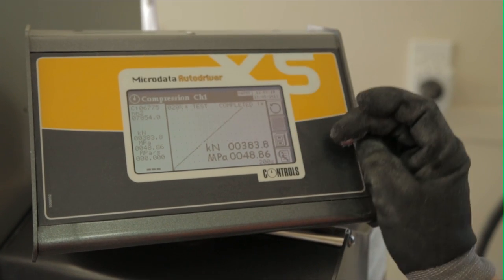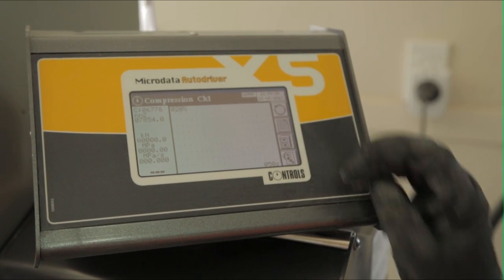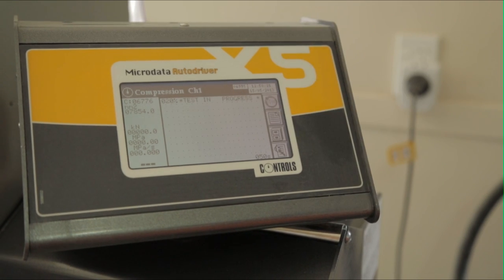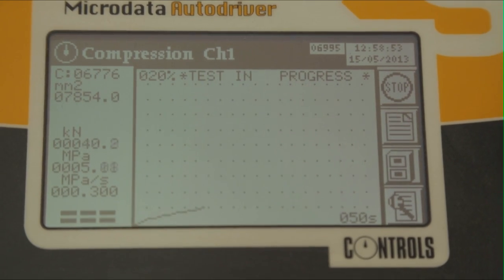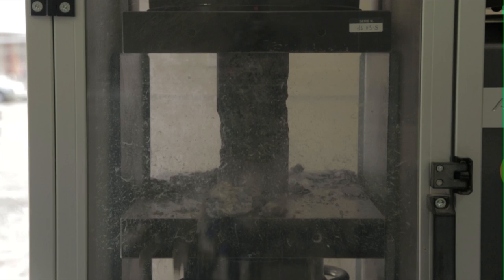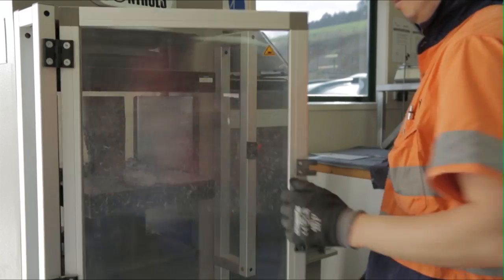Increase the load on the cylinder at a rate of 10 to 20 megapascals per minute. Generally aim for 15 megapascals per minute. Record the maximum load applied in kilonewtons, which is then used to calculate the cylinder strength.